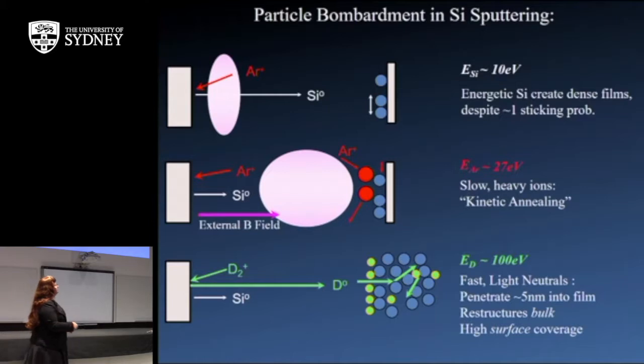You could also use hydrogen. It basically heals a lot of the defects in silicon. And there was something very interesting that people saw at this time, which is when they used deuterium instead of hydrogen, and I think you know what deuterium is, the solar cells worked better. Why would the solar cells work better if you put deuterium in there? People were really thinking hard about this and thinking, oh, there's got to be some phonon vibration, density of states change, and it has to be something really difficult. So we decided to figure that out.